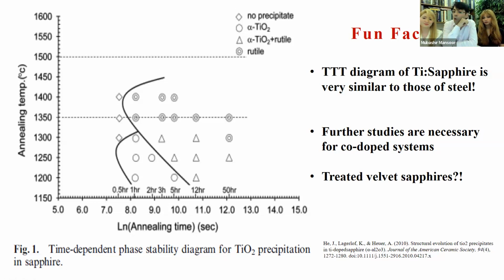But sometimes you want them to reappear. When do you want them to reappear? When you want to create velvet blues. What are velvet blues? Those sleepy sapphires are actually containing these very small particles of rutile that have been recrystallized in a very controlled manner. Nature does it beautifully in some geologic locations like the Kashmirs, but you can also do it in your furnace. And this paper by Professor Lagerlof back in 2010 actually plots the diagrams for how to do this, the kind of timings that you should do in order to have precipitates of rutile as you desire.